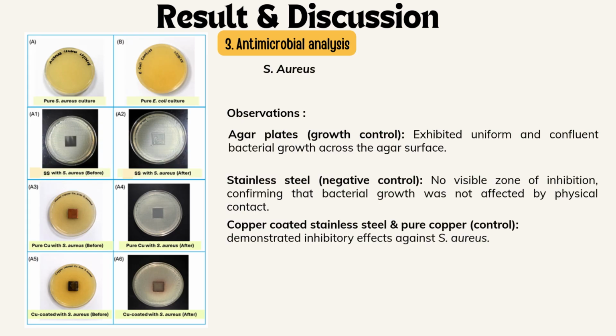Firstly, for S. aureus, agar plates were used as the growth control to indicate uniform and confluent bacterial growth across the agar surface. Next, stainless steel was used as the negative control to confirm that bacterial growth was not affected by physical contact. Next is the pure copper as the control to indicate the inhibitory effects against S. aureus.